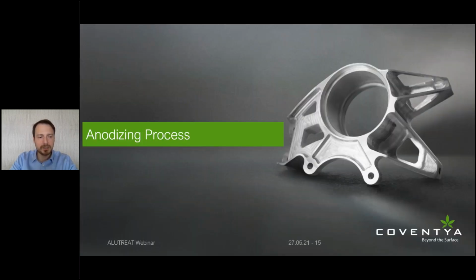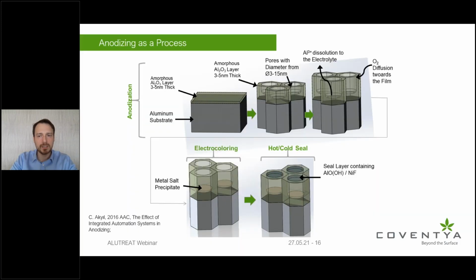So briefly, let's recap what is anodizing, because we're going to use this terminology a lot so that we are all on the same page. Per definition, anodization means loading the surface anodically or charging it, which means dissolving basically aluminum and growing the inherent oxide film, which is about 3-5 nanometers thick, to several microns. And this is something very interesting because you're basically dissolving aluminum by applying an anodic current, and instead of getting plated, it is converted to a porous structure.